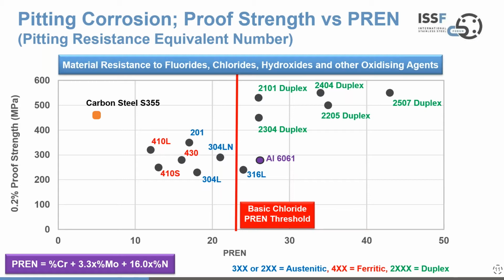And basically, what you see here is carbon steel, which is shown as a comparative material, and this sits in the top left, so has good strength but weaker corrosion resistance. And I think we'd all understand that. We've seen rusty carbon steel throughout our lives. And then in the right-hand side, to the right of the red line, which is described as the basic chloride pitting resistance threshold, you have the duplex family of grades that combine both high strength and good to excellent corrosion resistance.